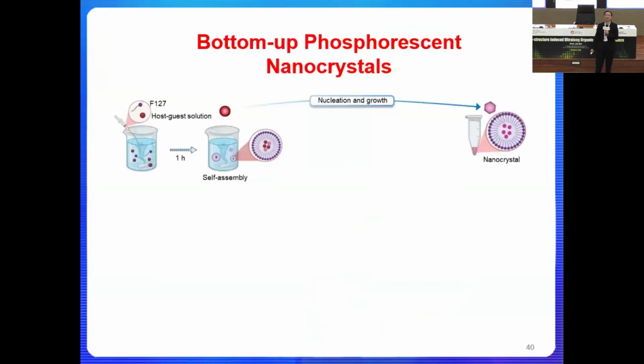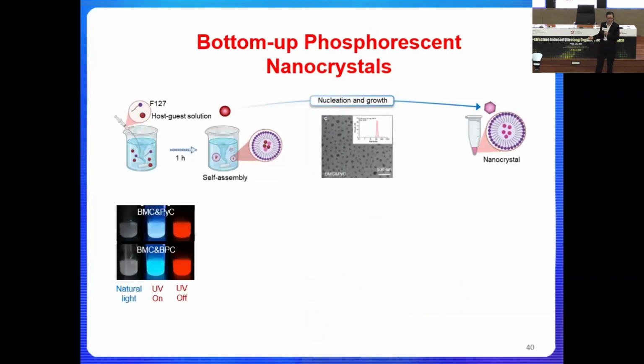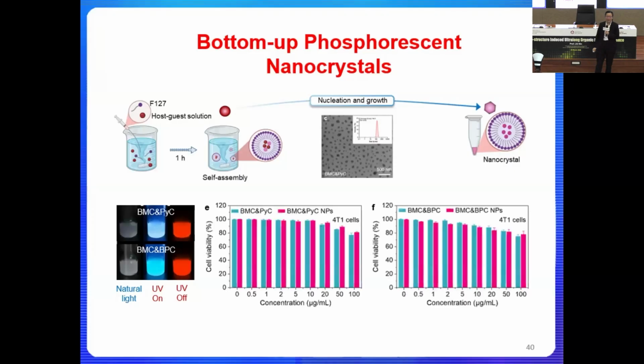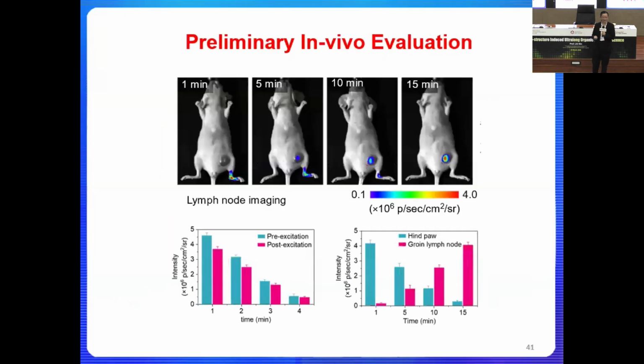So we just started this. We haven't really completed it, but we're happy to share that we are able to offer a bottom-up growth strategy with very well controlled size and morphology of the doped system, and bring them into the aqueous media. So we're able to get very nice room temperature phosphorescence in the aqueous media with a very well controlled size, about 50 nanometer. That is not very easy to achieve. All right, so we're in the process of studying the cytotoxicity of these nanoparticles, and we're also evaluating how effectively they can offer molecular imaging in the absence of light illumination and in the absence of autofluorescence. So the initial result is promising, and we're working continuously to demonstrate the biomedical applications.